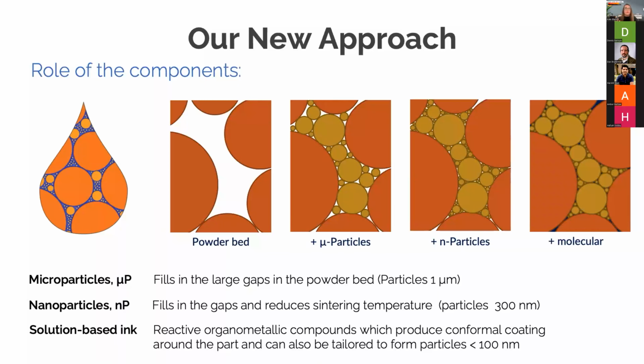and that forms either a metallic or a ceramic conformal coating. In this case here, you see this is just copper for an example. The micron particles then held within that binder, in that solution, fill in some of the interstices, some of those pores in the powder bed, and they can be up to a micron in size, depending on what print head you use, and that's why print heads are really important.